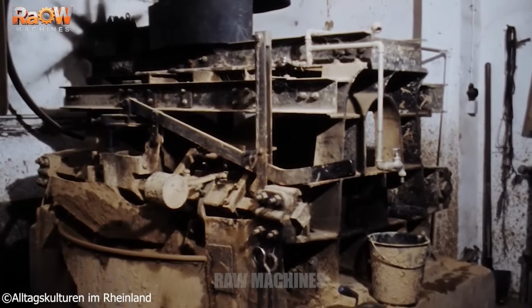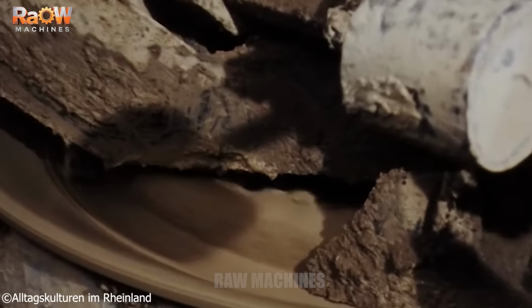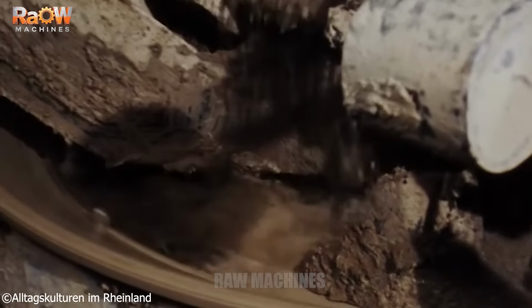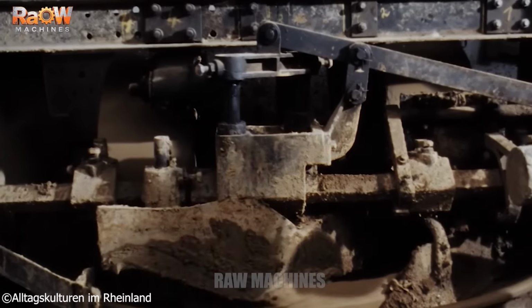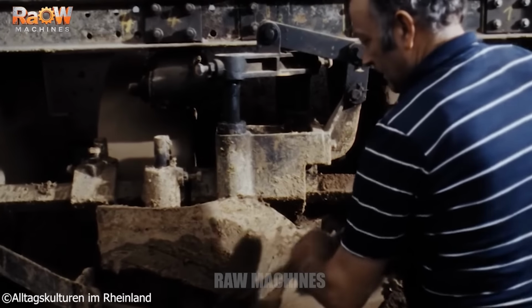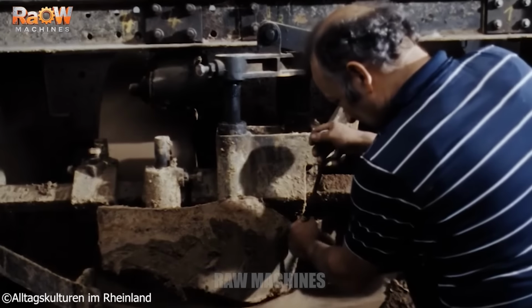The molding compound consists of clay mixed with horse manure, prepared in varying consistencies to suit each stage of the process. The clay is crushed and thoroughly blended in the foundry's clay room to ensure fineness, plasticity, and adhesion, while minimizing cracking during drying and withstanding the high temperatures of casting.